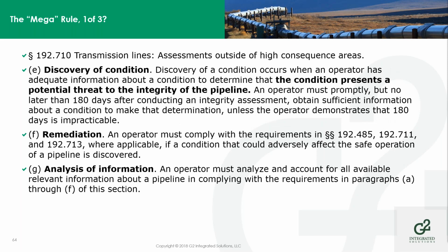Discovery of a condition occurs when an operator has adequate information about the condition to determine the condition presents a potential threat. You must promptly, but no later than 180 days after conducting an integrity assessment, obtain sufficient information about the condition to make the determination. Much of this language is the same. The operator must comply with remediation under 192.485 and 711 and 713 if a condition could adversely affect the safe operation of the pipeline. In an analysis of that information, you must account for all available relevant information about the pipeline in complying with this requirement.